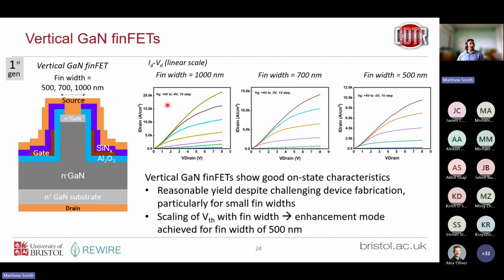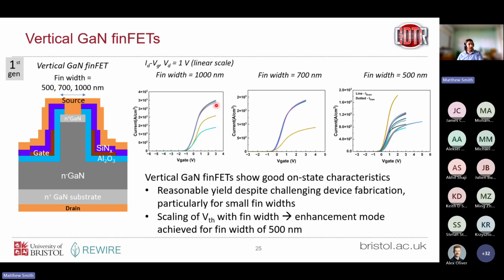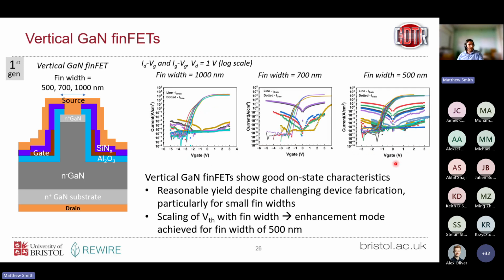So fabricating our devices, we see good news for this first generation is they seem to work quite well in the on state. So we've got something that looks like a transistor characteristic, nice linear ohmic contacts here, and our drain current, or output current, is increasing as we increase our gate bias. Looking at the transfer characteristics, again, confirms we've got reasonable characteristics. We can see the threshold voltage scaling with the fin width, which is what we expect based on our simulations. Reasonable gate current, so not too many problems with gate leakage in the on state.